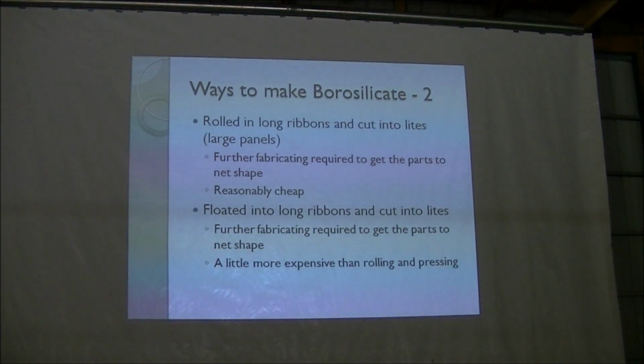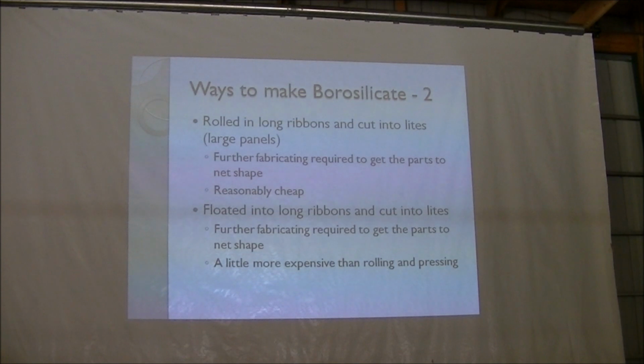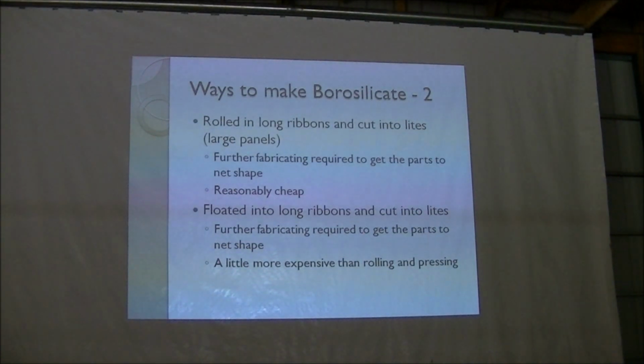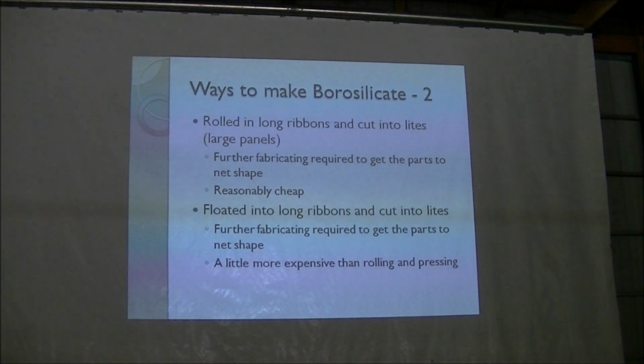They say, well, why would you pour the glass into melted metal? Well, tin melts at a much lower temperature than glass, but the glass has a lower specific gravity than the tin. So essentially what you're doing is it's almost like pouring hot oil onto cold water. Well, or hot fat. You pour hot fat onto cold water, you have a layer of congealed fat on top. That's exactly how windows are made today and architectural glass is produced today. It's a pretty good analogy.